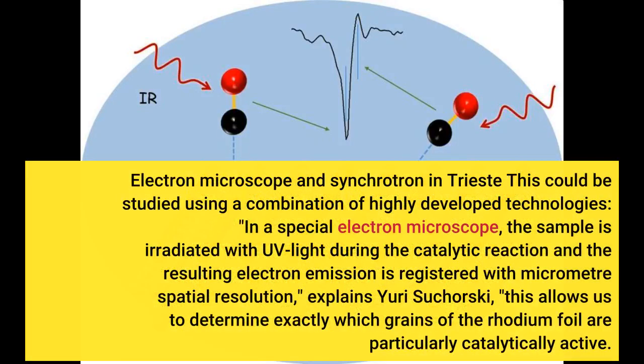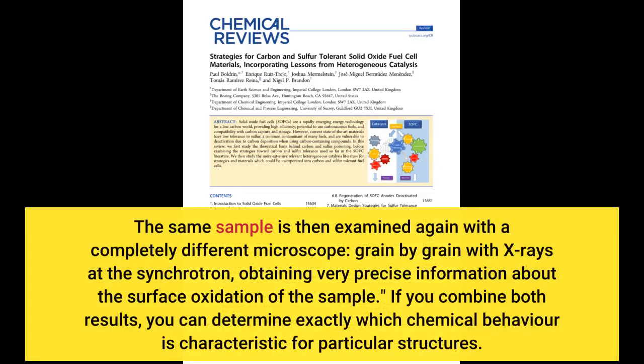Electron microscope and synchrotron in Trieste. This could be studied using a combination of highly developed technologies. In a special electron microscope, the sample is irradiated with UV light during the catalytic reaction and the resulting electron emission is registered with micrometer spatial resolution. The same sample is then examined again with a completely different microscope, grain by grain with X-rays at the synchrotron, obtaining very precise information about the surface oxidation of the sample. If you combine both results, you can determine exactly which chemical behavior is characteristic.